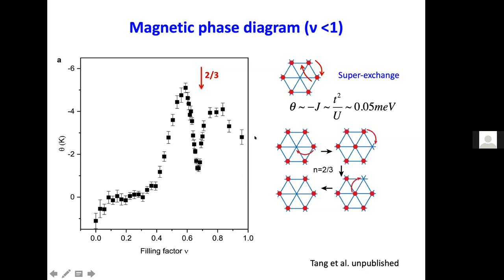So if you naively just have this type of hopping, you can have a t squared over U contribution, and that energy is a little bit bigger than what we observed here. So what I was saying is that if this is a perfect triangular lattice, and I'm showing just one possible channel, but if you can come up with all the 180 different combinations of this hopping and add all of them together, they actually cancel. This is done by my colleague, Elsa, by the way.